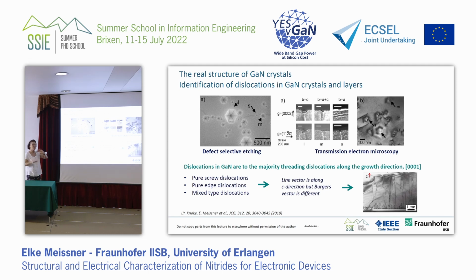And if we do something like defect selective etching, you can see that, for example, if you etch the surface of the crystal by a wet chemical etch, for the nitrides, for example, this is a KOH, NaOH melt under high temperature, under 400 degrees C. Then you see that at any place where there is a dislocation, you see in the transmission electron microscopy picture this shape of the etch pit, and underneath you can then see by the g·b criteria what type of dislocation is underneath such an etch pit.